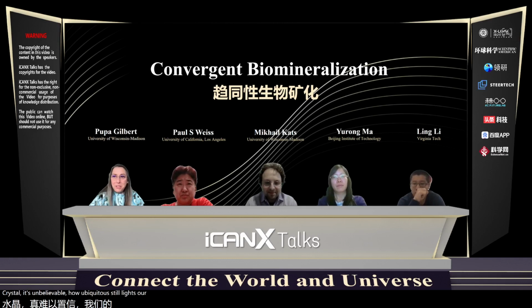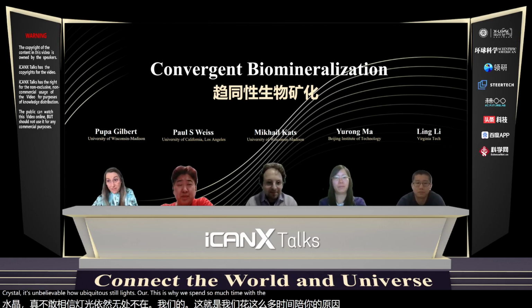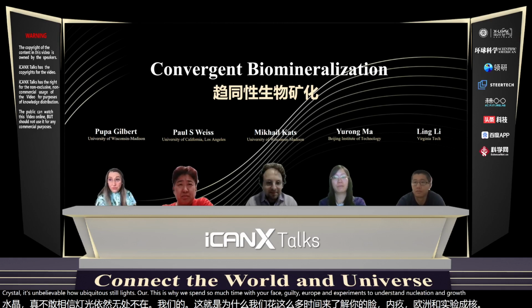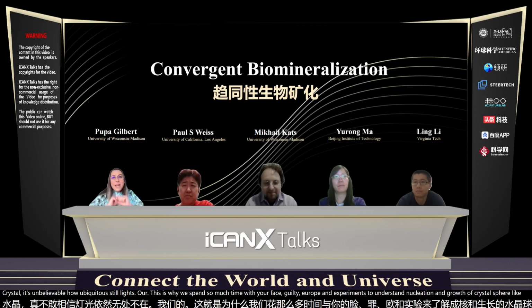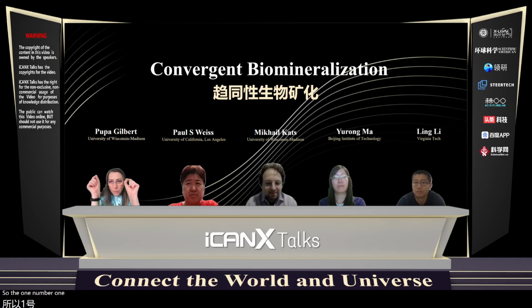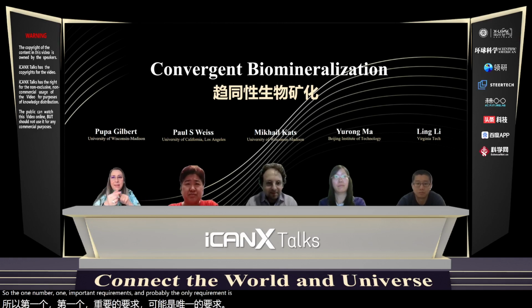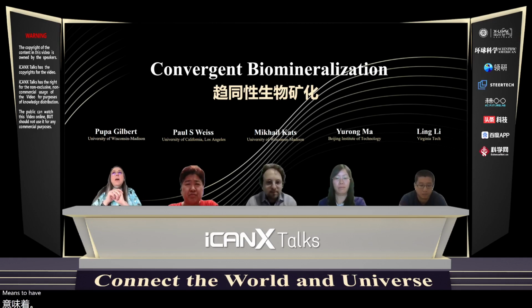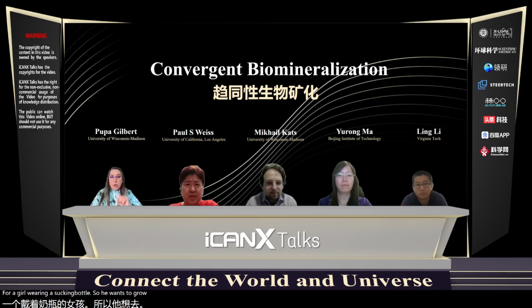This is why we spent so much time with the phase field theory and experiments to understand nucleation and growth of spherulite crystals. So the number one important requirement, and probably the only requirement, is that a crystal needs to have a propensity for growing acicularly. So it wants to grow long with a long aspect ratio, make a needle.